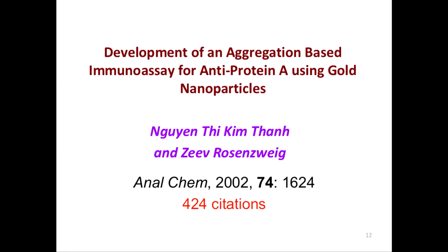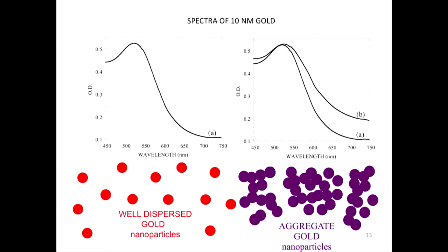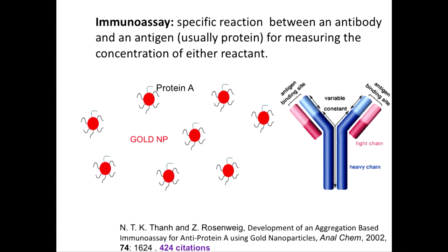So what is the application of the gold nanoparticle? One very simple application is the aggregation assay, an immunoassay. Fundamentally, when gold nanoparticles are very well dispersed, you will see a very distinctive absorption at 520 nanometers. Light is an electromagnetic wave that interacts with the electrons around the nanoparticle, and this is different when they are well separated or aggregated. So you will have a change in absorption at longer wavelengths, and this is the color change from red to blue.